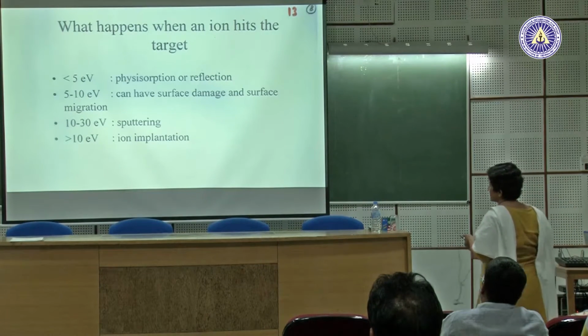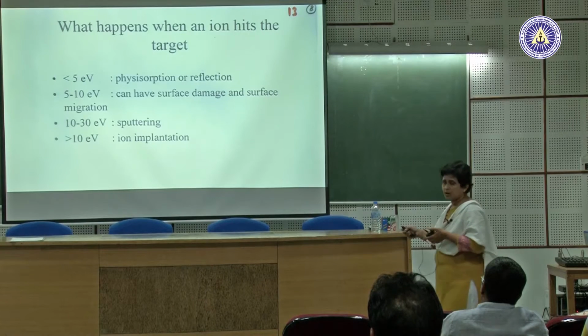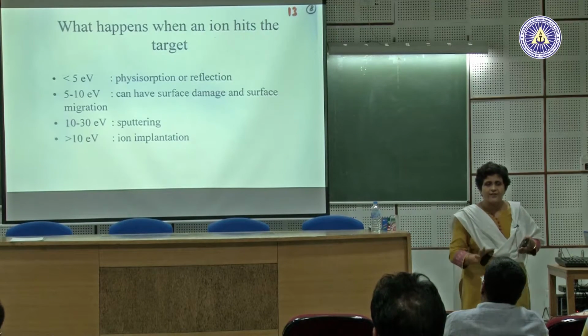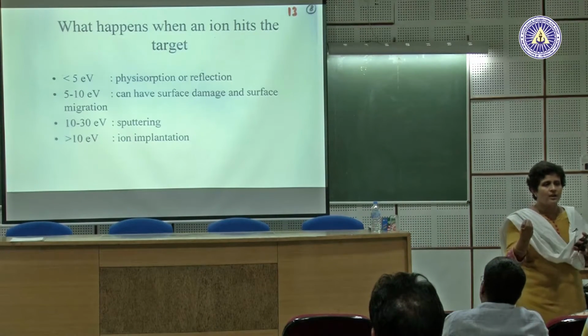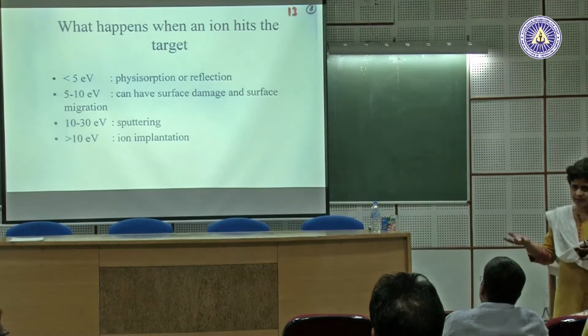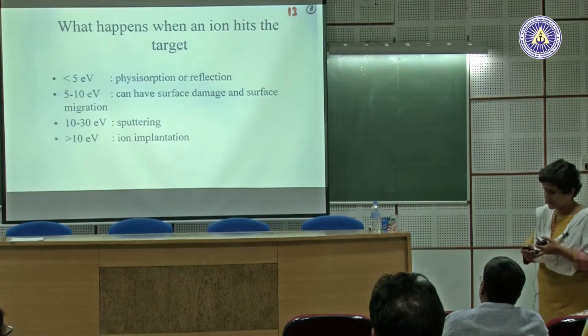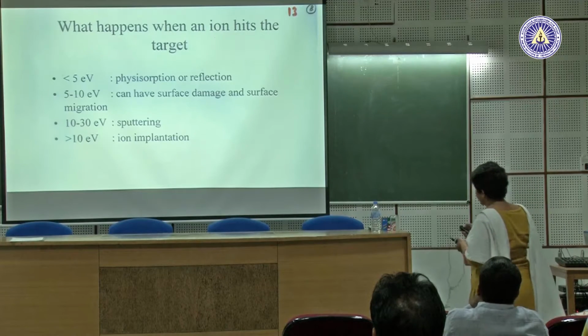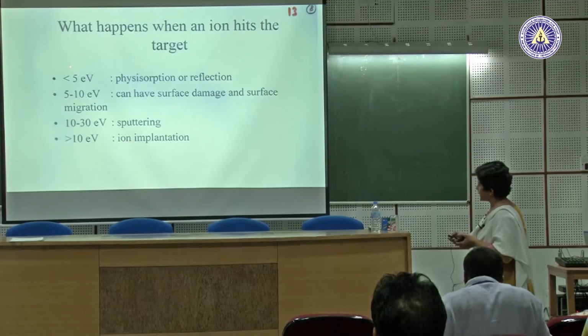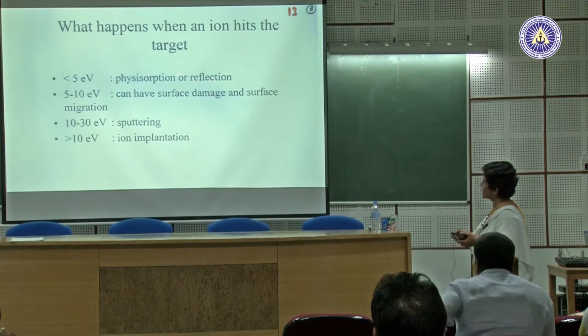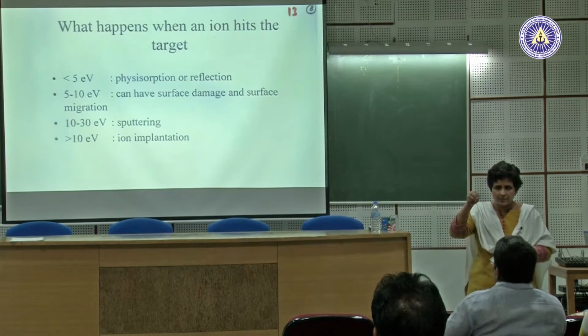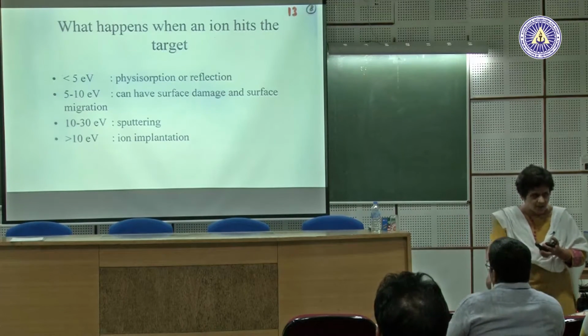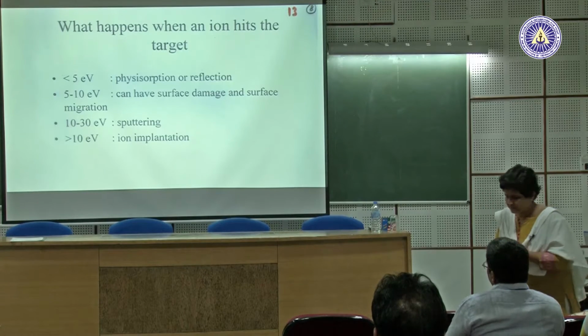So, if you are doing thermal evaporation, the energies are not going to exceed 5 electron volts. You can do that calculation of what the equilibrium thermal energy is, and if an atom gets evaporated, what that energy will be. But in the case of sputtering, in this particular case, you have either physisorption or reflection. If an atom comes with low energy, it will get accommodated or it will get reflected.